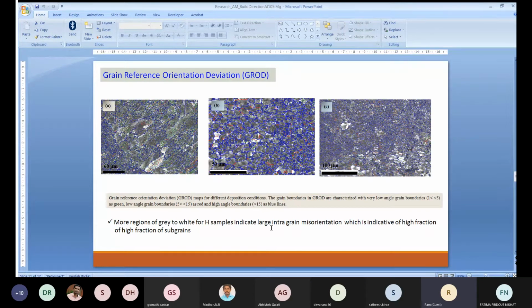So you can see the grains with different colors inside. You have to look inside the grain. If the color changes from blue, green, gray, and white, moving in this direction, and you have more and more gray and green, it means that you have more intra-grain misorientation. So as you can see very well, in figure A you can see more gray and white regions, which indicates a large intra-grain misorientation. In other words, you have more subgrains and higher dislocation density inside the grains.